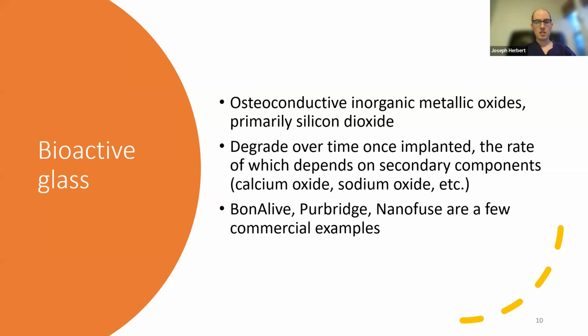Bioactive glass has gotten quite a lot of talk. It seems like, from my perspective, it's gotten quite a lot of talk over the last 5 to 10 years. This is an osteoconductive, inorganic metallic oxide. Usually it's silicon dioxide. That's what most of the commercially available bioactive glasses are. These degrade over time once they're implanted, and the rate at which they degrade depends on the secondary components. So they're primarily silicon dioxide, and then they usually add calcium oxide or sodium oxide in varying quantities.